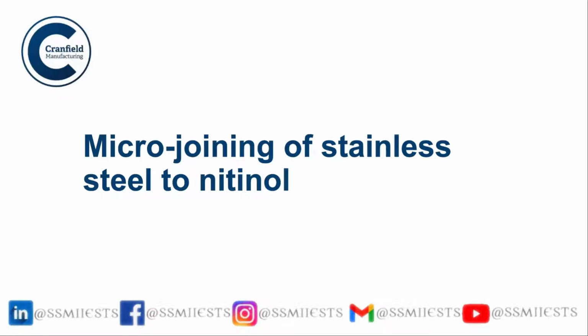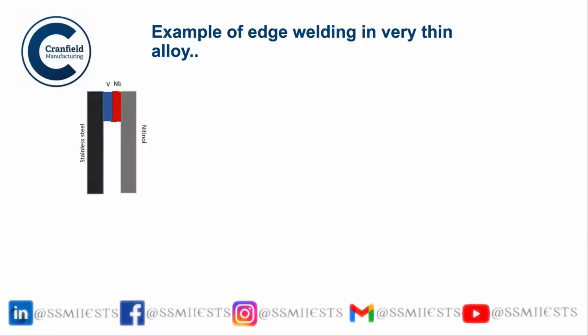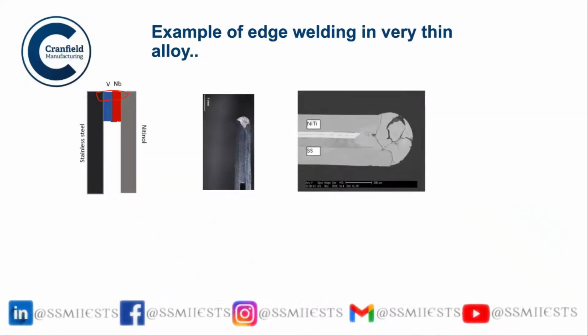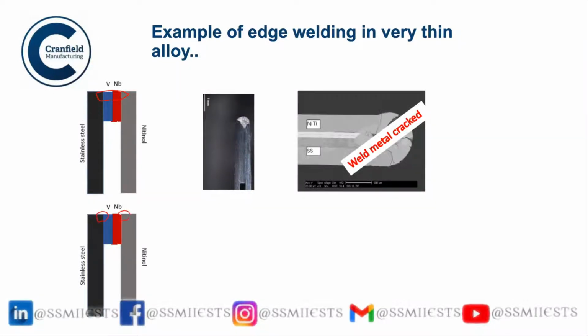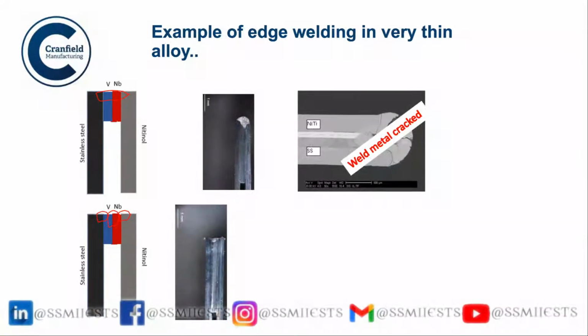So a study was done in our center to understand how we can form joints. If you recall my previous schematic explanation, in the same way we use two different interlayers. One is vanadium, the other is niobium. Vanadium is good with stainless steel, niobium is good with nitinol, and vanadium and niobium are good with each other. But if you form a weld like this, what happens? It completely cracks, because the titanium atoms can travel through the melt pool and form the intermetallic on the other side. However, if you do separate welds between vanadium and stainless steel, niobium and nitinol, and then vanadium and niobium, it is possible to achieve a joint.